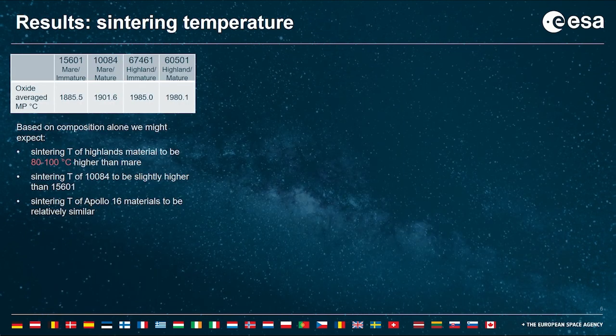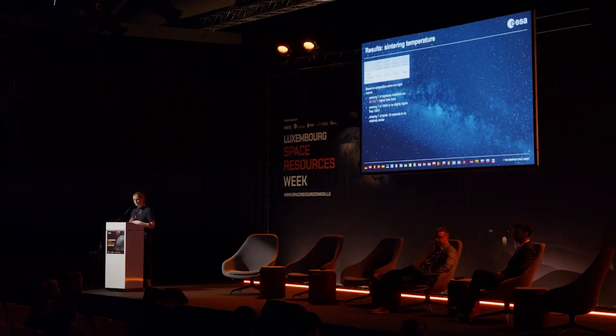So to go on to the results, we wanted to first look at what we might predict in terms of melting behavior based on the composition and comparing the materials to one another. So we looked at the weighted average oxide melting point, because the oxide content is probably one of the first things we might know about a material at a given landing site. Of course, the material is not made up of pure oxides, but we can say in general that if there's a high quantity of a high melting point oxide, for example, calcium oxide, in a given mineral, that will raise the melting point of that mineral relative to if it's got low melting point oxides in it, for example, sodium oxide in plagioclase. So based on composition alone, we might expect that the sintering temperature of the Highland material would be 80 to 100 degrees higher than Mare.